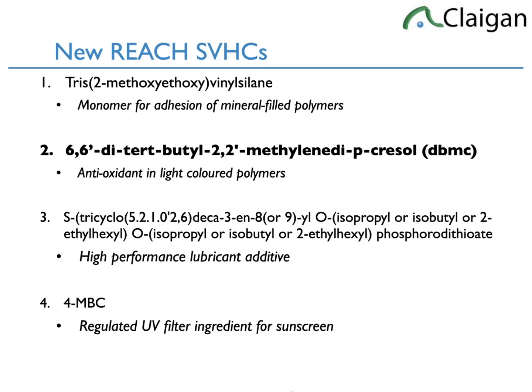Now, the monomer will generally be fully reacted into a polymer, but there might be some trace residual monomer. But in the REACH SVHC, the 1000 ppm limit is over the weight of the article, the component. Any chemical that's governed by a safety data sheet does not fall into that until it's added to the physical item. So if this is adhering a piece of glass and a piece of plastic together, any residual monomer in that adhesive is measured over the weight of the adhesive plus the glass piece plus the plastic piece. And at that point in time, the risk of the residual monomer being over 1000 ppm is virtually nothing. So that's low risk.